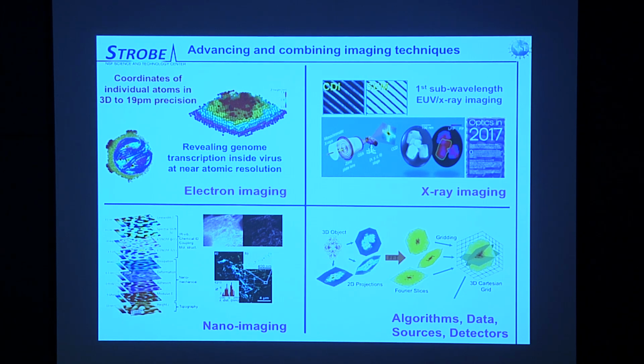And that's why you have this amazing advance in electron imaging these days. This is work from Jianwei Miao at UCLA, who has identified nanoparticles. This is one example where they could take a 7 nanometer nanoparticle and identify the positions of over 26,000 atoms and know exactly which atom was which, to be able to see defects, screw dislocations, just amazing.